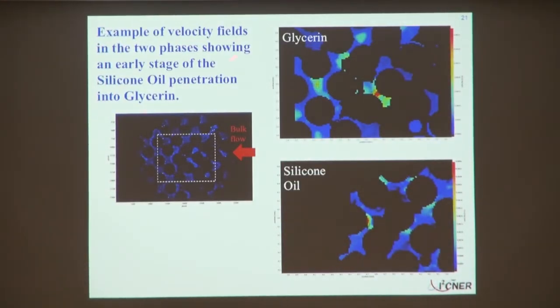So here's examples of fluid velocity fields, which is effectively a measure of the flow rate of the two phases through the pore structure. Okay? And so here's a zoomed in region of the porous structure. On the top you can see the glycerin phase, and on the bottom the silicone oil phase. Where there's glycerin, there is not silicone oil. Okay? And so you see that in this particular time snapshot, segmented regions of glycerin, and you see the front of silicone oil passing into the pore structure. And we can measure then quantitatively the velocity or the flow rate through these pore pathways.